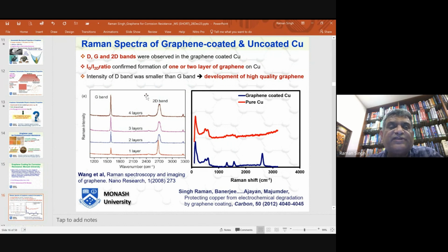When you do Raman spectroscopy, you get a spectrum to confirm whether you got graphene or not. Graphene has this typical spectrum where you have the G peak, this peak is the G peak, and the 2D peak. The presence of these two peaks confirms the presence of graphene. So what we got from Ajayan's group had graphene, and that is the critical confirmatory information about graphene.